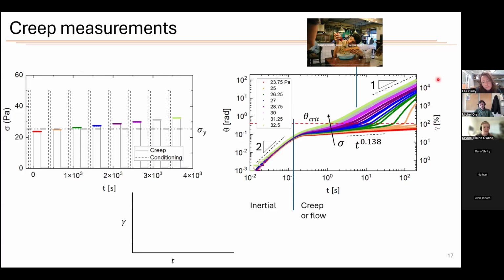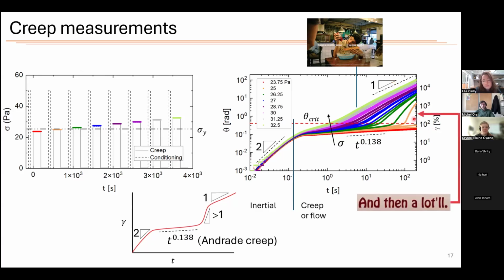So overall, what we've seen here is if we follow what is the displacement or strain as a function of time, we get a little bit of inertia, we have a very low level creep, and then in the most exciting case, we have a very sudden rise, which depending on the case, can have a slope that is much higher than even inertia, but in most cases, it's even higher than just the steady flow state. And this is the part that is where all of the ketchup comes out.